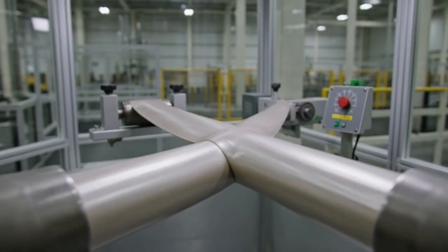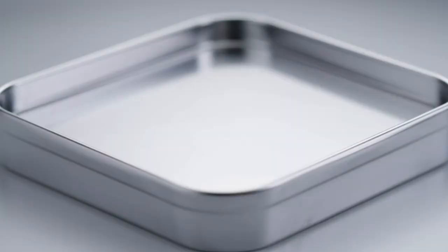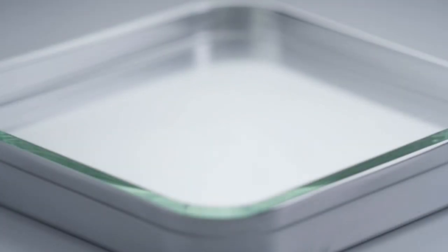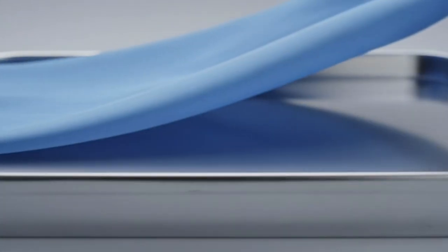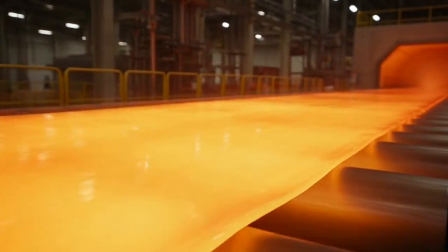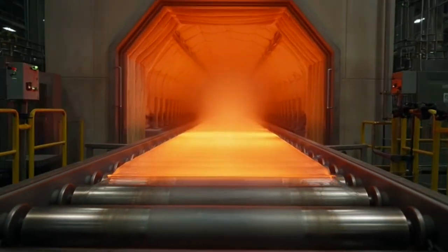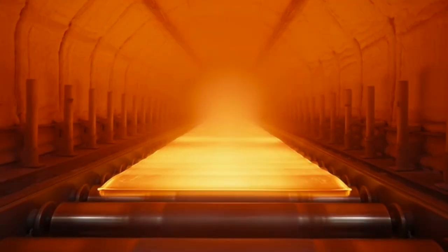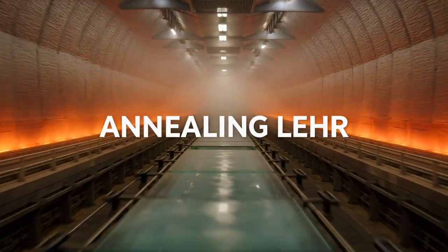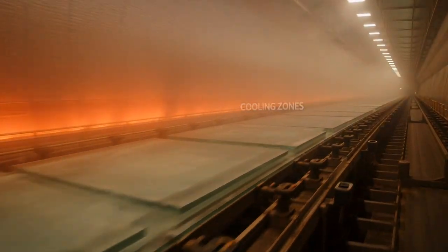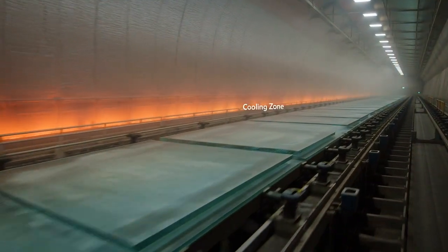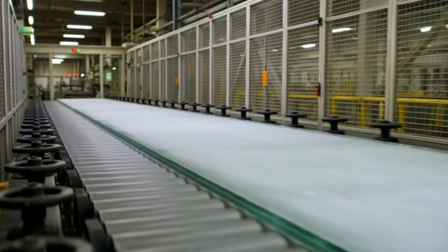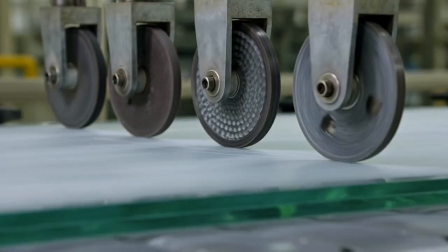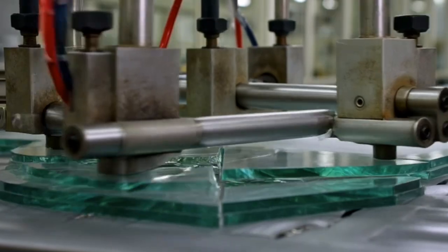Now, the magic part. It flows onto a long bath of molten tin in an oxygen-free atmosphere. Nitrogen plus hydrogen, so tin doesn't rust. Glass is lighter, so it floats. Gravity and surface tension flatten it into a perfect ribbon, no contact marks, both sides polished naturally. Thickness is controlled by how fast you pull the ribbon and little edge rollers. You can dial it from super thin, like phone screens, to thick structural glass.